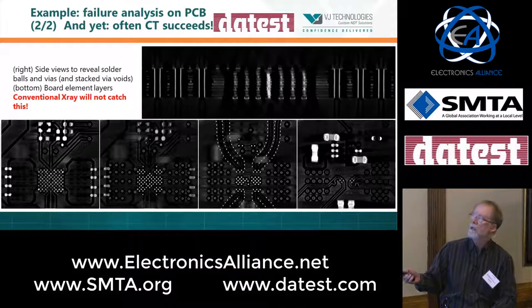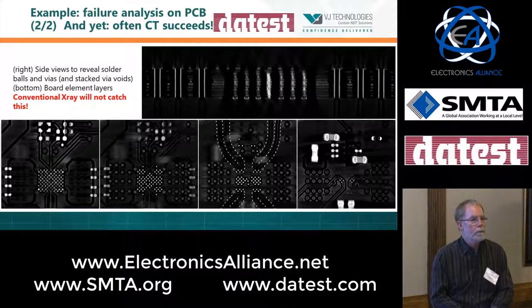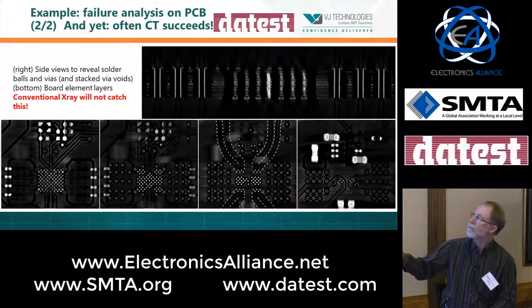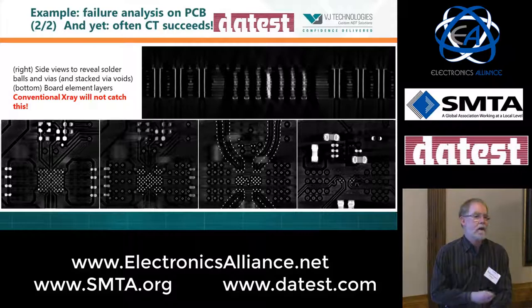Individual layers. This board had an intermittent open. And the source of the intermittent open was that little dot you see right there, which was both a void and a crack. And under any kind of mechanical stress, it was interrupting the transmission on that particular circuit. That was the source of the failure in this case.